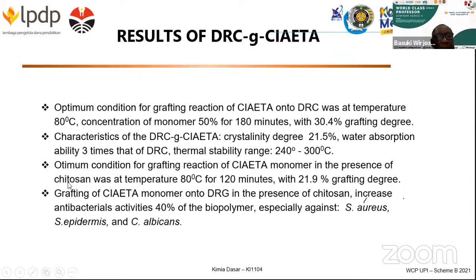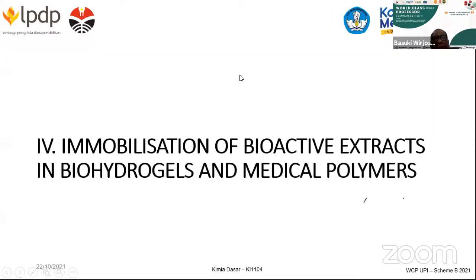Okay, and then if we add some chitosan here, the grafting degree is also not very high, only around 21%. But if we put some chitosan in the grafting reaction, the antibacterial activity improves, especially with these 3 types of bacteria. We know that chitosan also functions as an antibacterial agent.